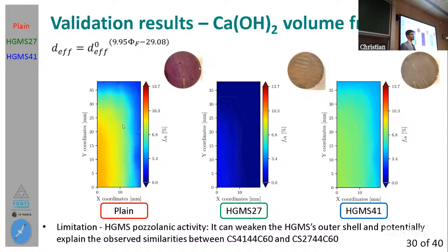Then I want to show you the results obtained for the HGMS27 cement paste. There you will see that we don't have this pattern of colors anymore, and instead we have a complete blue coloration, indicating, as you can see in the scale there, a zero concentration or volume fraction of calcium hydroxide. This correlates very well with the results obtained in the pH indicator test, where we have a complete consumption of calcium hydroxide. And this happens because we have also included this possible fracture of the spheres. The spheres broke under these conditions of 20 megapascals, using the results obtained in the MIP on powder samples. Then this porosity increased, and this affected the effective diffusivity. So it was easier for the CO2 to be transported within the cement matrix and affect the whole cement matrix.